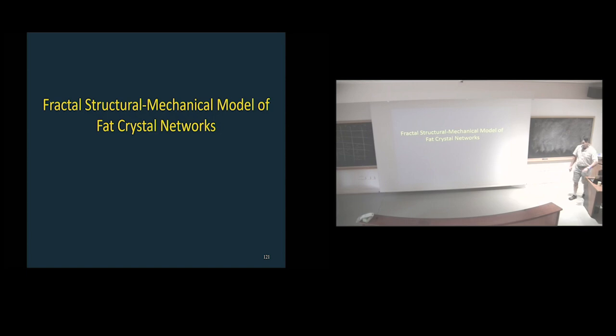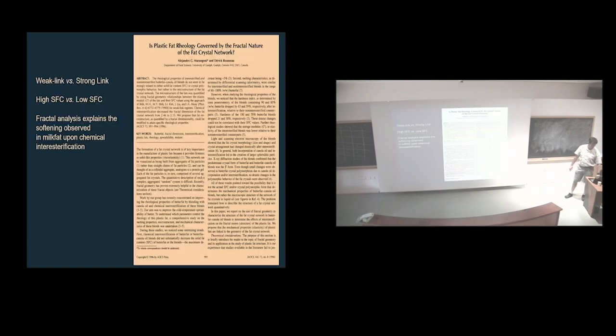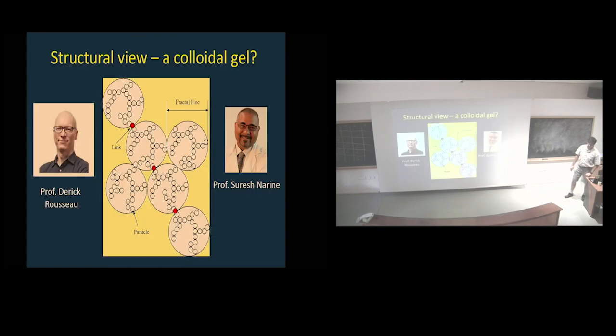I just wanted to show you this. This is finally what we consider to be a fat crystal network. This will take one minute. Clusters made of particles. The particles are the nanoplatelets. Of course, they're spherical here. And they interact by very weak link. I just wanted to make sure that you understand we're not in the classic strong link regime. We assume that these are hard and this is soft. That's the only way I can see how a ball transduces mechanical energy to the next ball. I cannot see how a string of cotton balls can transduce anything, but that's my fault. So these things are hard, and the good regime is in between. Makes it simpler too, even though not correct.